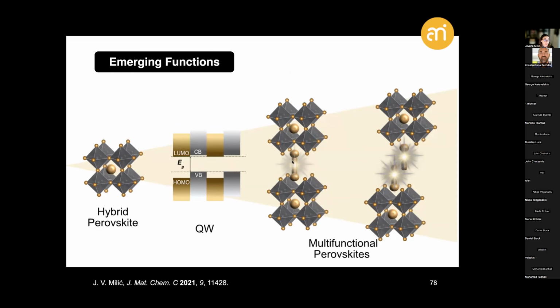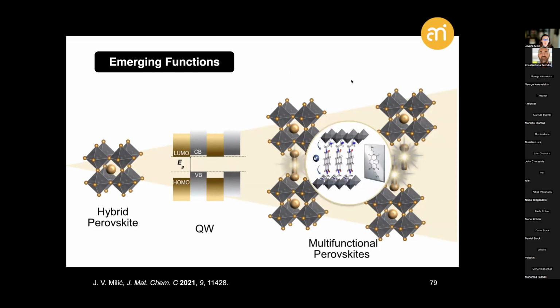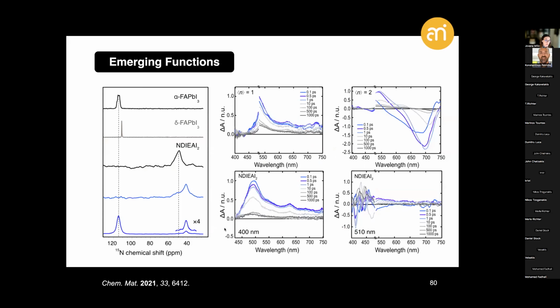in this case electroactive, further contributes to the process and stabilizes the system without compromising the resulting performances of the materials, which we have been very invested in, such as by using some of the electroactive spacers, as illustrated here, based on naphthalene diimides or NDI moieties, extended to form bifunctional Dion-Jacobson architectures, which have already illustrated the capacity to contribute to stabilizing some of the formamidinium layered hybrid perovskites that are also underrepresented, revealing